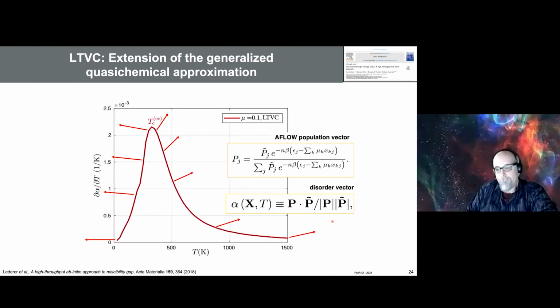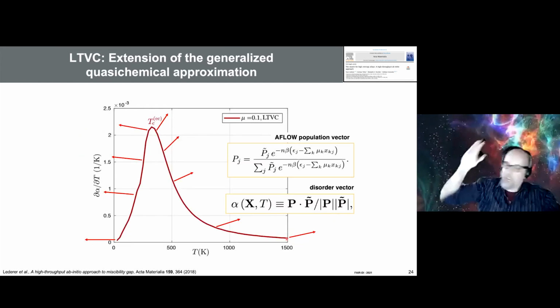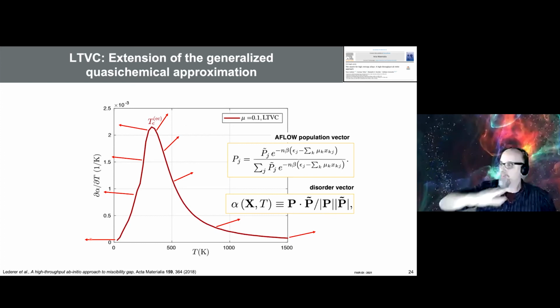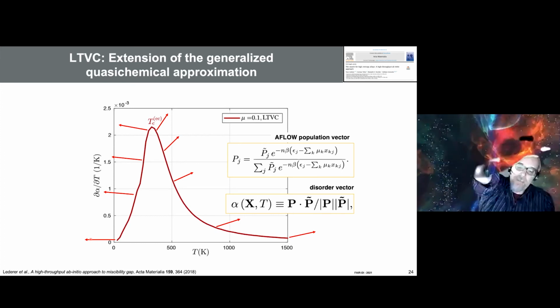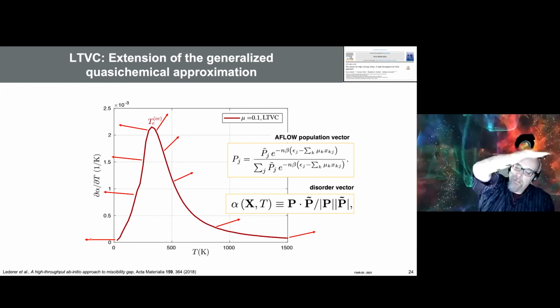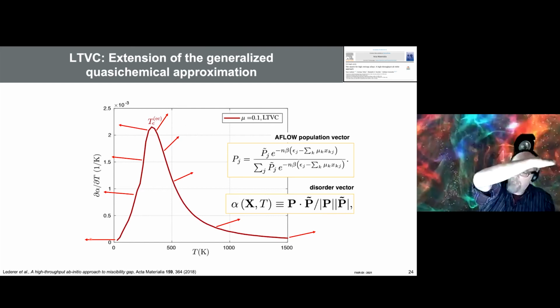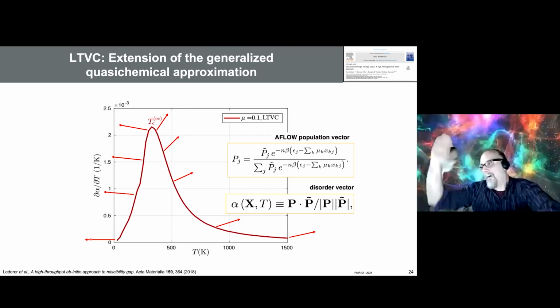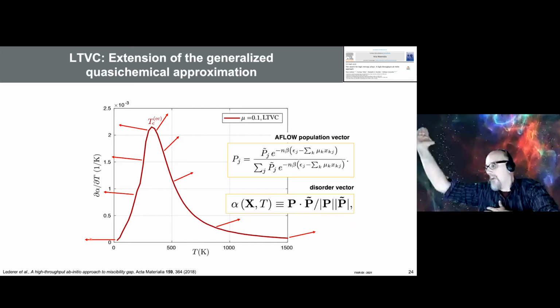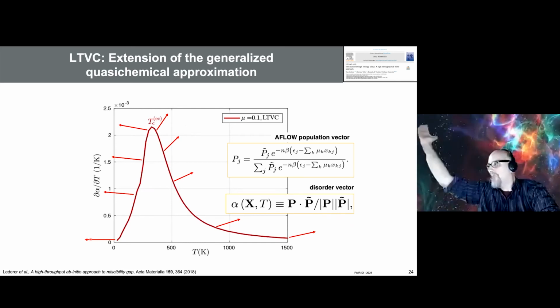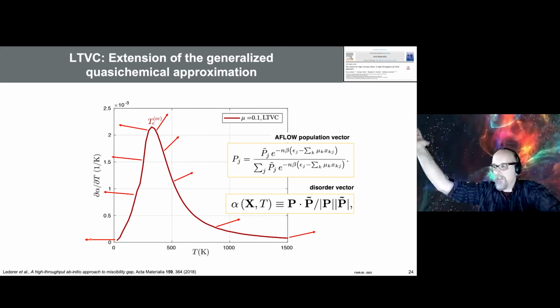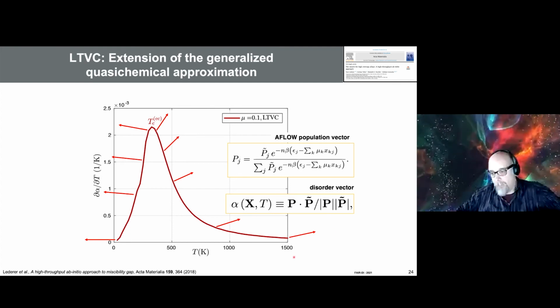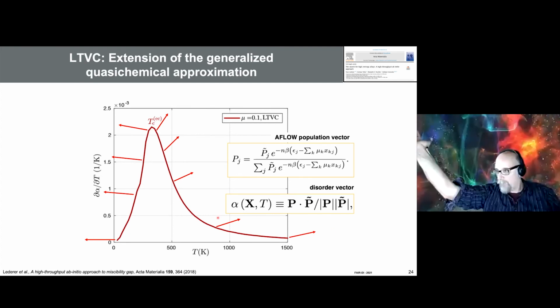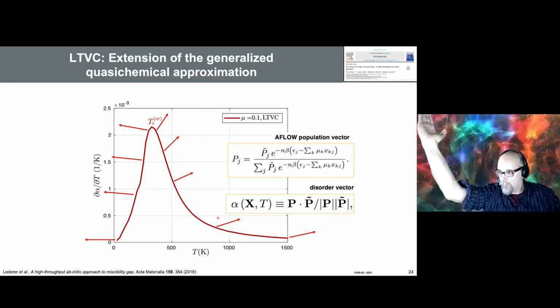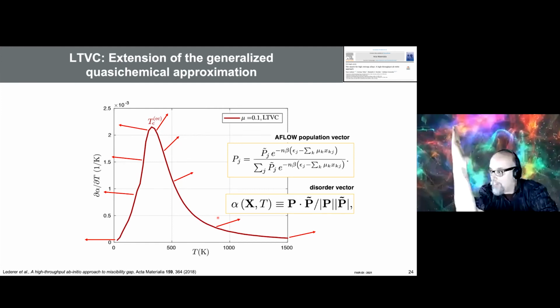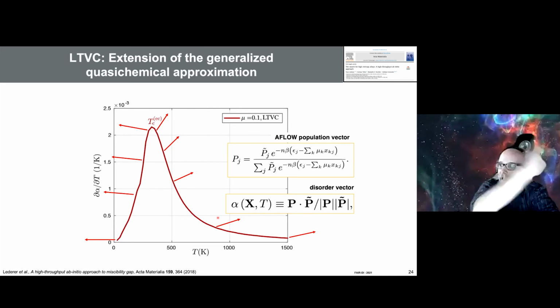Here it is. At infinite temperature, well, let's go to the simple one, zero temperature. At zero temperature, you have only one, two, or three phases appearing. So the vector is well defined. At infinite temperature, and you look at my arm here, everything is equiprobable, so the vector is going to be in different directions. If you reduce the temperature here, the vector changes. You see, as you reduce the temperature, the vector moves slowly, slowly, bam, until it has a big jump.